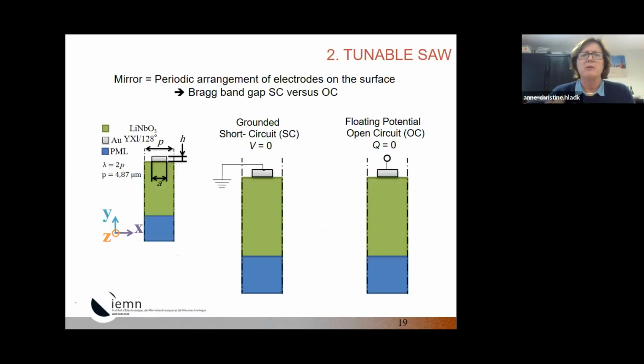A Bragg mirror is a very simple device. It's only a periodic arrangement of electrodes on the surface of the piezoelectric substrate. So you have here only one electrode of the mirror. You have the lithium niobate substrate, and here you have PML. First, on the electrode, you put a short circuit, and you get a band gap. Second, the same but open circuit on the surface, and you have another band gap. And this shift of the band gap will help us to have a tunable resonator.